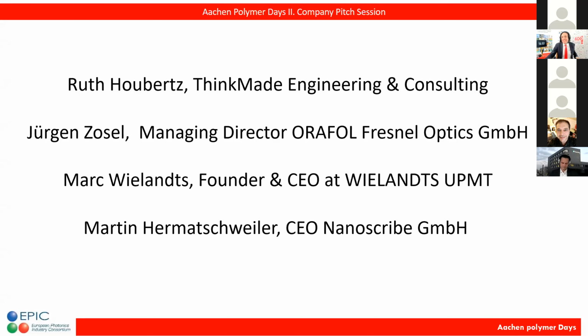Yeah, I think the material or optical polymer is every time a huge challenge, because I remember about 25 years ago, we developed, I would say, still today, the best material which is available. It's a PMMA, and the big challenge for us is to release this material from a microstructure, because it's very hard as long as you have not just the slope, also a draft, which is very hard to release the material, and therefore we have special releasing components included in the material. But on the other hand, you should not see this included releasing material in the optical component, and it should not influence the transmission. So it's very, very hard to find the right material.